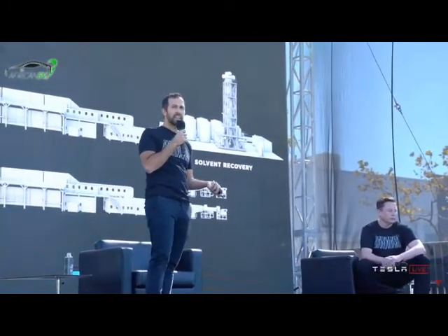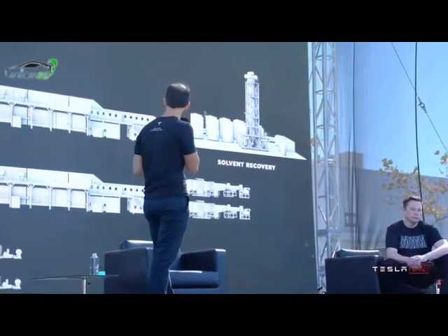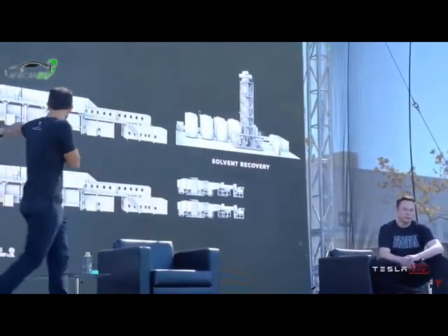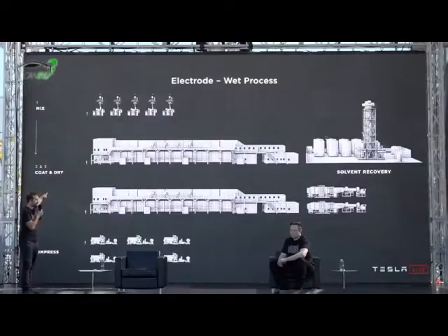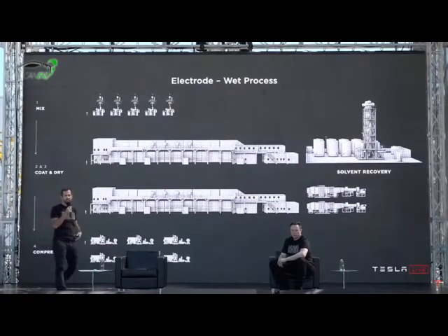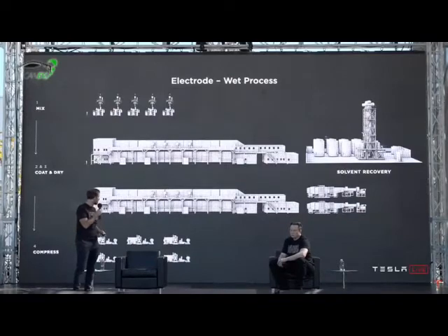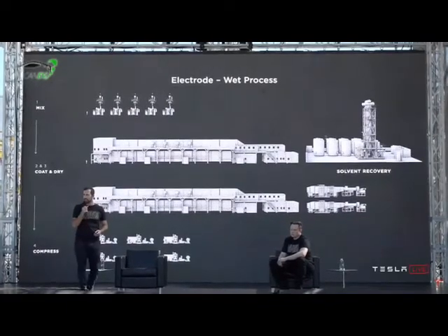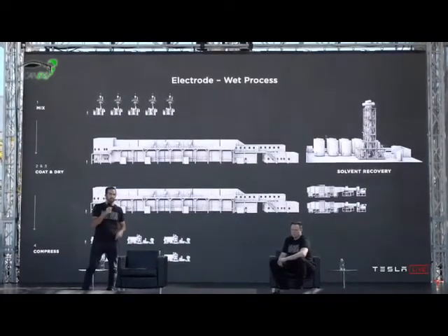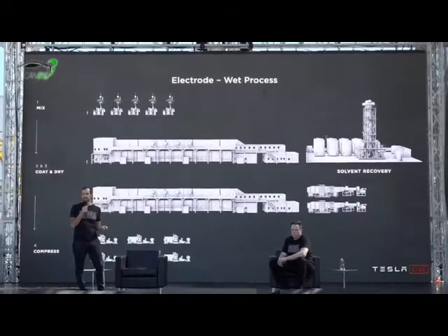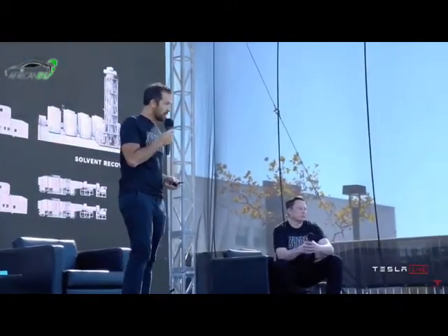When you're looking at this, you're like, wow, that's a lot of equipment for one step, especially when you consider that little speck next to the coating oven is a person. This is serious iron involved in making batteries. Wouldn't it be great if we could skip that solvent step, which is one of those dig a ditch and then fill it kind of things, where you put the solvent in and then take it out and recycle it, and just go straight to dry mix to coat? That's what the dry process really is about.